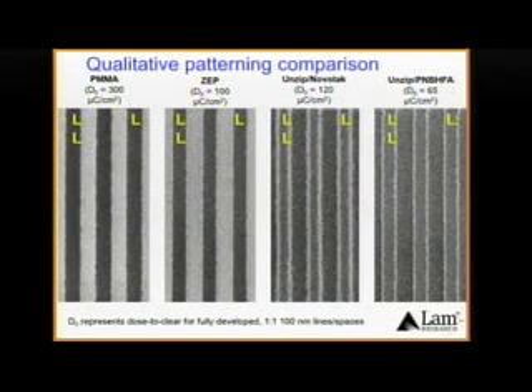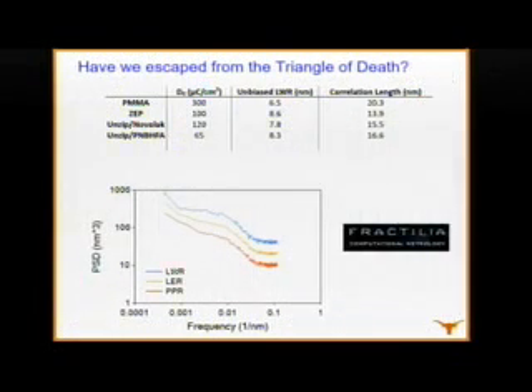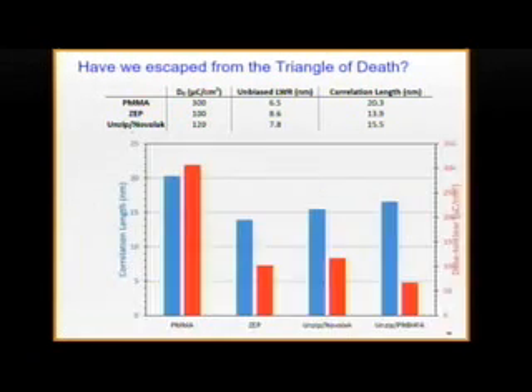So we made a whole bunch of resists and engaged this company whose job it is to measure line edge roughness quantitatively. And they measured a bunch of things that I didn't really fully understand, the correlation lengths and the power spectral distribution and so on. But the key thing is that what you want is to have a long correlation length, which means smooth sides, and a low dose. So the blue thing should be long and the red thing should be short. And so generally, if you shorten the red thing, according to the triangle of death, the blue thing should go with you.